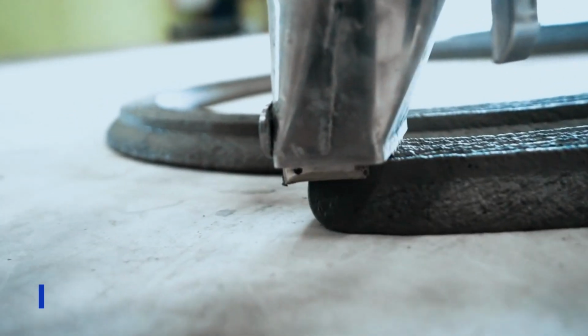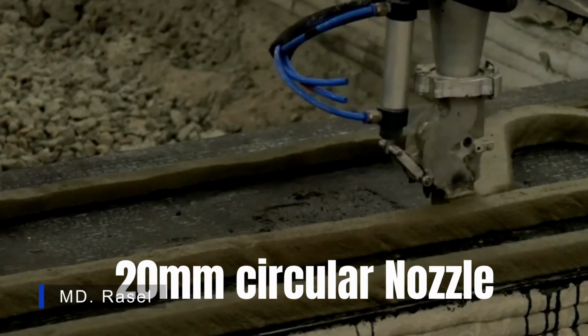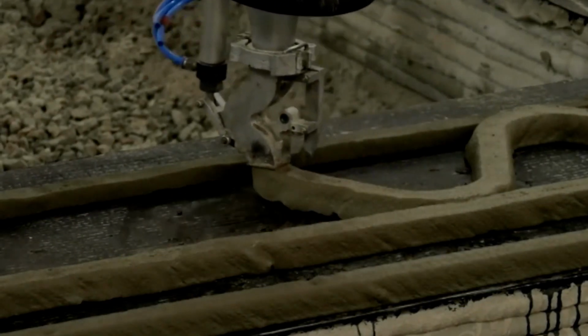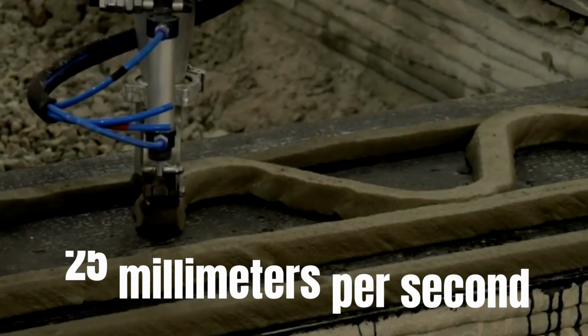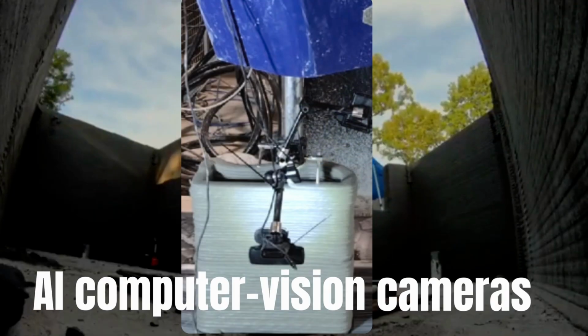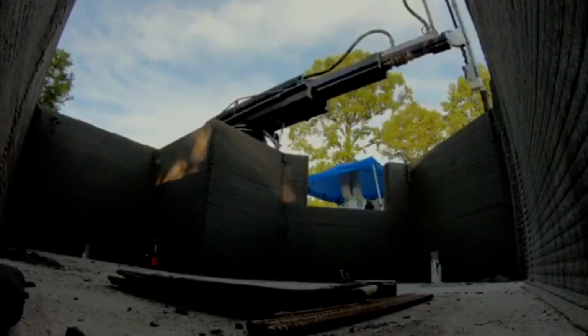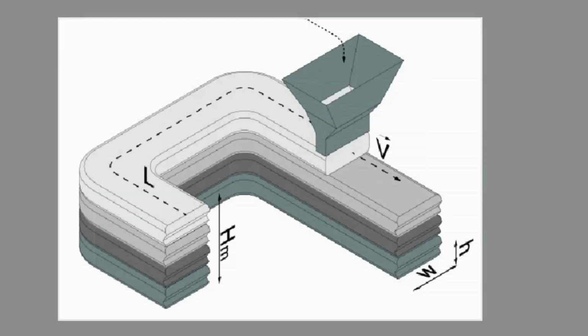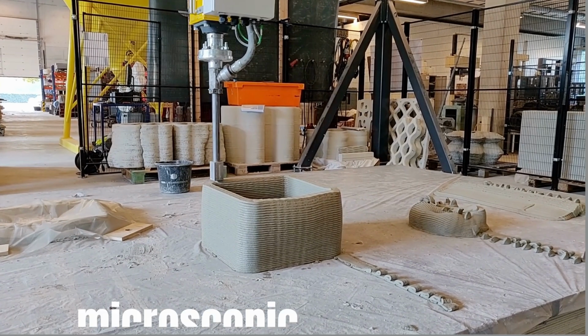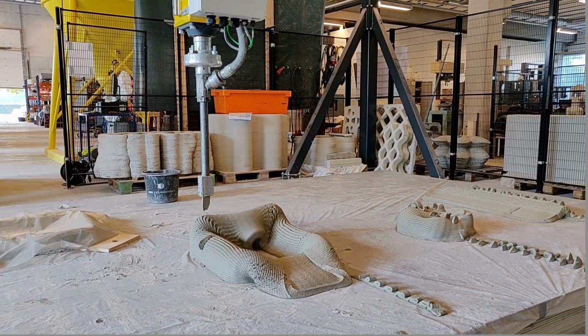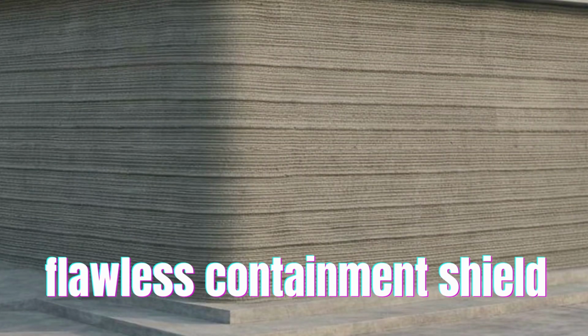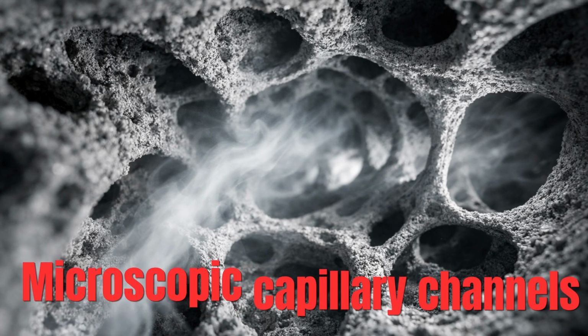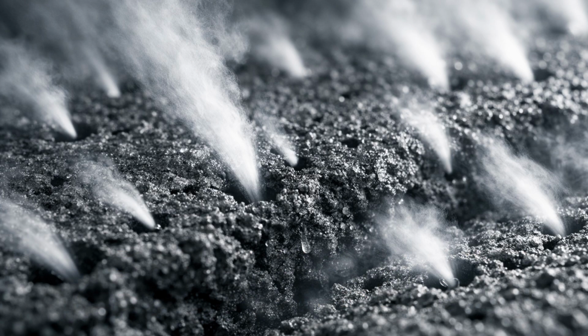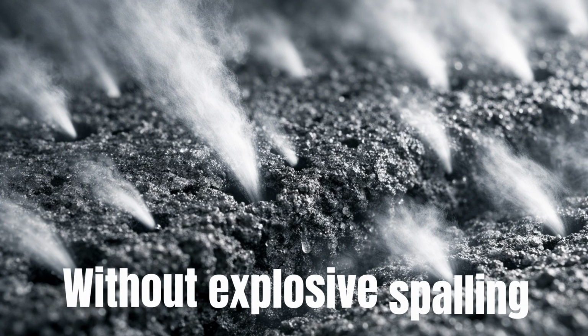3D printing here utilizes a 20 mm circular nozzle with a precise printing speed of 25 mm per second. During this extrusion, AI computer vision cameras monitor the structure in real time. They continuously analyze the layer height and width, detecting any microscopic buckling or poor adhesion to guarantee a flawless containment shield. PVA fiber naturally melts at 230 degrees Celsius, leaving behind microscopic capillary channels. The pressurized internal steam simply vents through this path without explosive spalling.